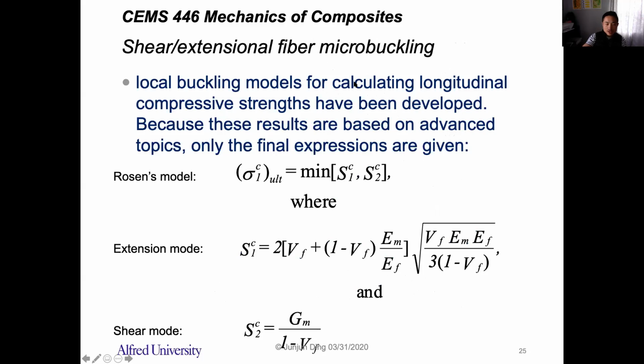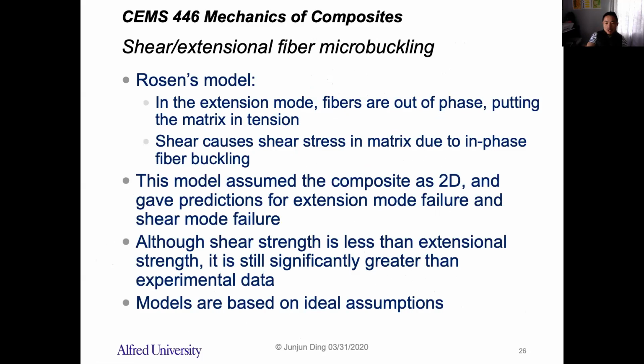Okay, so this is the model that evaluates whether this composite will fail in the extension mode or the shear mode in the microbuckling. But still, this model is not perfect. There's a lot of assumptions here, and you may find this model doesn't work really well with the experimental data. There may be other models for more precise prediction. So for this model, they assume the composite as 2D. So it gives the prediction for extension mode or shear mode failure.